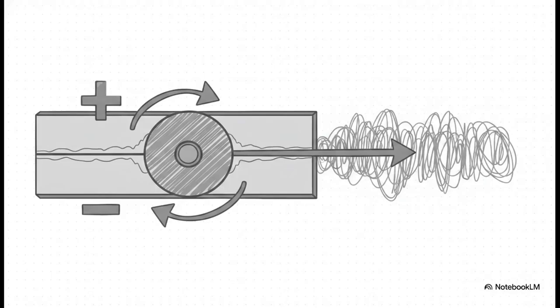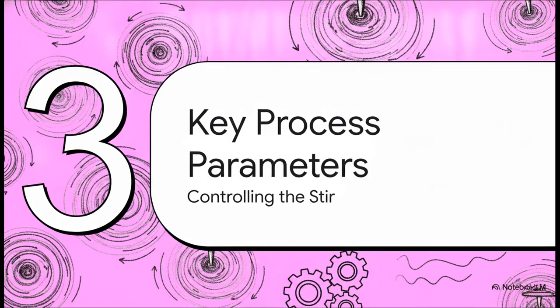And the physics of this gets really interesting. Because the tool is spinning incredibly fast while also plowing forward down the weld seam, the forces on either side are totally different. On what's called the advancing side, the spin direction is exactly the same as the forward travel direction, so those speeds actually add up. But on the retreating side, the spin is fighting against the forward motion, so it subtracts from the overall speed. Because of this crazy dynamic, the inside of the weld nugget is inherently asymmetrical. It's exactly why procedures have to strictly specify which way the tool rotates. If you get it backward, the metal won't flow right, and you've literally just ruined a wildly expensive piece of aerospace aluminum.